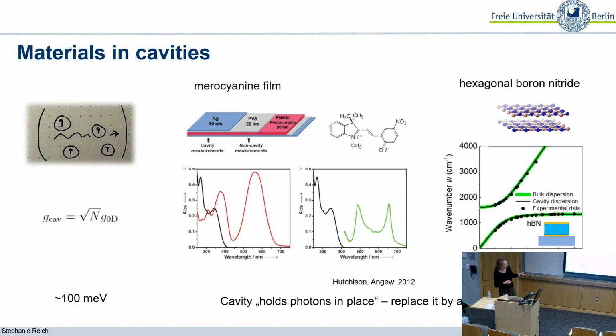So this is when you look in the part of the sample where there's only the bottom cladding but no top cladding. And then when you go to the cavity, it splits into two peaks, and they correspond to these lower and upper polaritons that I've introduced before.